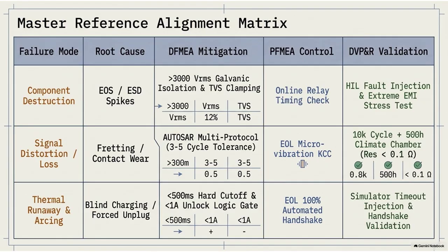And this is where the engineering really has to prove itself. Because after those 500 hours of extreme thermal and chemical abuse, they pull the plug out of the chamber and they measure the electrical impedance. The strict requirement is that the electrical resistance between the pins must remain below 0.1 ohms. 1/10 of a single ohm.